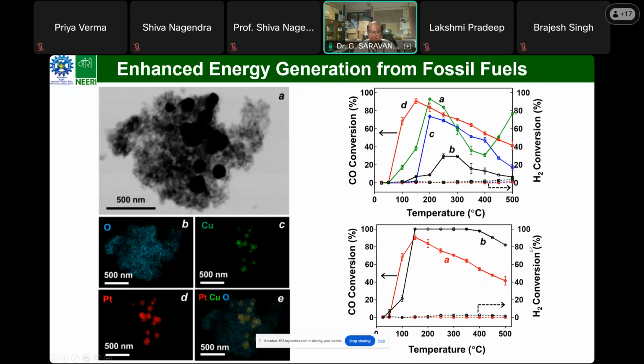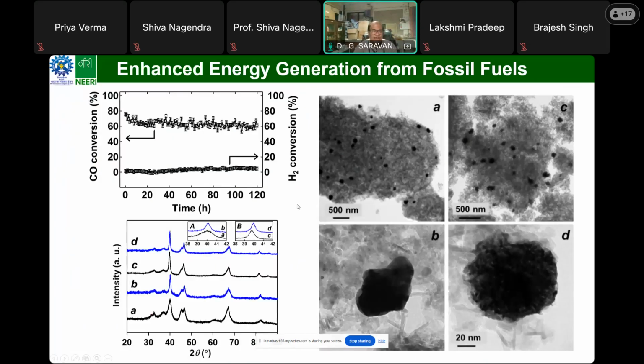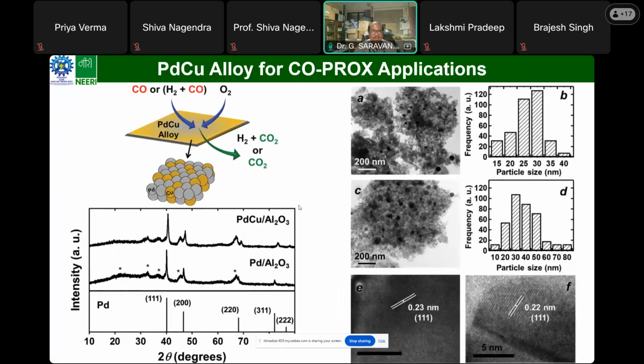That means even when increasing the oxygen concentration in this hydrogen-rich stream, CO can be selectively removed. That is the takeaway message from this experiment. We have done stability testing up to 5 days, and it is quite stable. We can selectively remove CO gas, and although there is a slight compromise, this is reasonable for durable performance. We also ensured structure stability and morphology, and the PtCu core-shell structure has the potential for removal of CO from the hydrogen-rich stream.